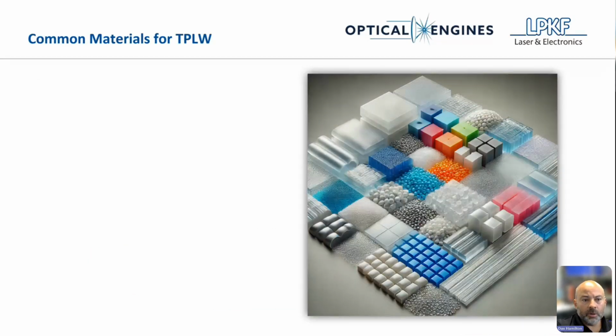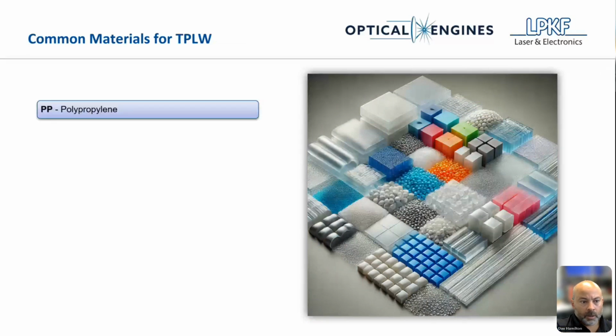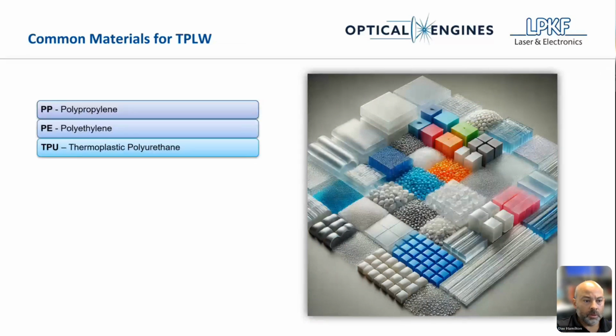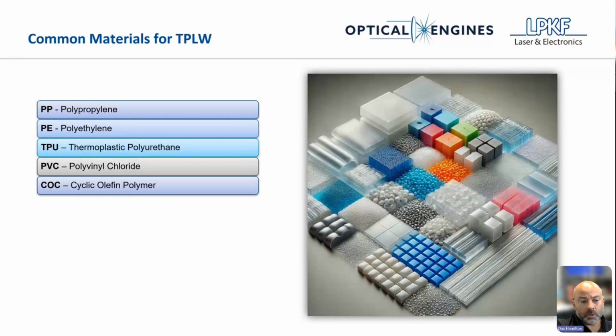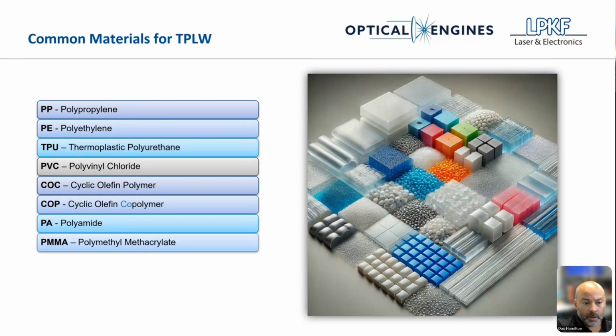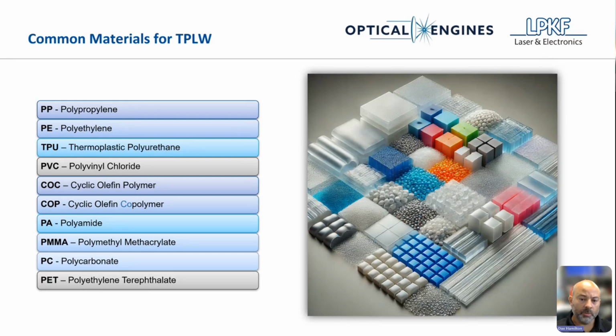All right, let's talk about some of the common materials, and I'm going to go through these really quick here. Polypropylene, polyethylene, TPU, thermoplastic polyurethane, PVC, cyclic olefin copolymers, so COCs and COPs, very common materials for TPLW, polyamide, and PMMA, as well as PC. That's the last one here. Oh, and PET. These are some of the most common materials we've seen over the years, and they all bond quite well with transparent polymer laser welding. I would say they're more or less in order from easiest to bond to some of the more difficult. Some of the PETs, PETG, are difficult materials because the process window is pretty small and it tends to burn or bubble up quite quickly.